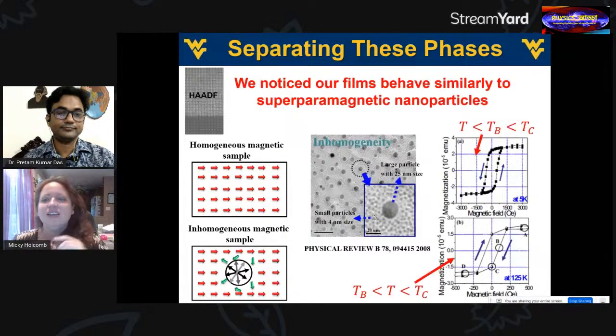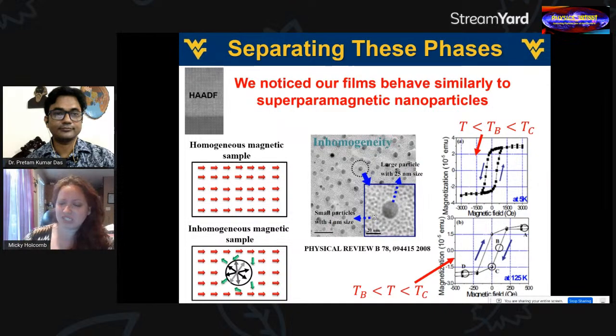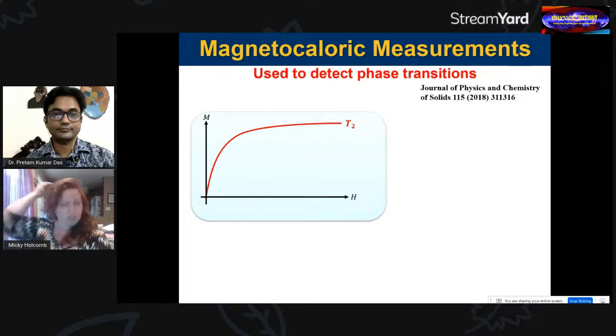But it turns out that superparamagnetic nanoparticles do this similar thing with inverting their magnetic hysteresis loops. So that's how he got interested in that. So, they have a similar inversion in the hysteresis loops. So there's this method, a magnetocaloric method, used to actually detect these different phases in superparamagnetic nanoparticles. So in those particles, sometimes you can have competition between a ferromagnetic phase and superparamagnetism. So here's how they look at it.